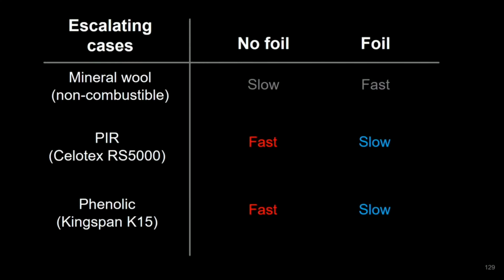I analyzed the heat released by all of these insulation products from the start of each experiment until the time at which the escalation of the fire occurred, and I found that the contribution to the total heat released from the combustible insulations with foil facers up to the point of escalation was measurable but minor. In the cases of combustible insulations without foil facers, I found that the contribution to heat release up to the critical time, i.e. the point of escalation, may be comparable to that of the ACM itself.